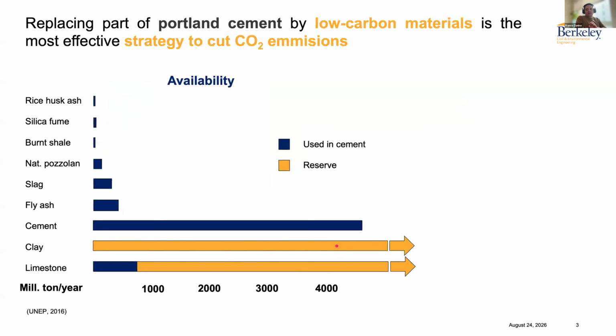The other aspect that is very important and that I want to highlight at this point is that several strategies for the decarbonization of cement and concrete have been put forward over the years. And I think that by now there is consensus that the most effective way of decarbonizing this quickly, at least in the time frame from here to 2050, which is not a long time left that we have, is to use low carbon materials or mineral additions to reduce the clinker factor in our cements. And this is something that we have been doing already for decades, right? There are the usual suspects like slag from blast furnaces and fly ash.